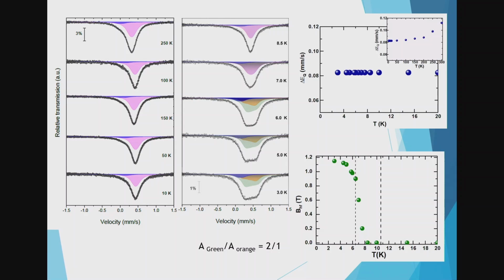So you really have to choose what is the best fit for this material, because all the parameters are very sensitive, they are in the same range, they are competing very closely, so it's difficult to see. Yes, single crystal could help, but this material is so easy, it's congruent melting. The only thing I didn't do for this sample was heat treatment, which helps to have homogenization of the material. So that's my fault. But anyhow, it helped to understand better what kind of fitting we should do.